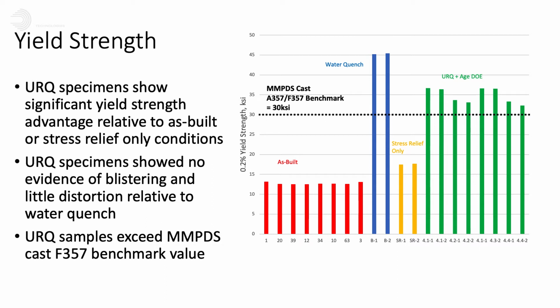And what we found is that the results from the ultra rapid quench process were pretty good. They were very close to what we were seeing in our baseline water quench samples, and they certainly exceeded the benchmark values for F357 that we see in the MMPDS materials handbook. So it was a fairly positive result that we saw when we made these trials. And then we decided we would repeat a few different conditions to see how robust that was.